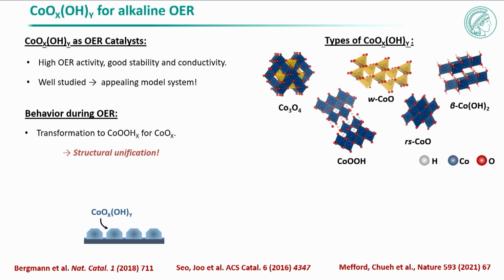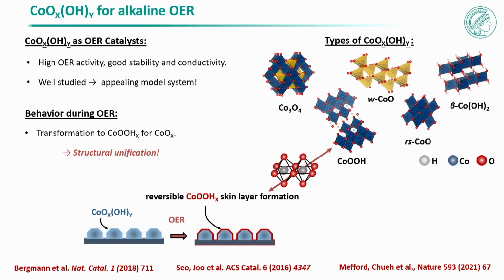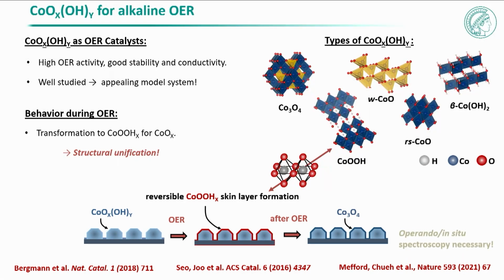So you start with a cobalt oxide or hydroxide, you put it in your electrolyzer, you apply the potential, you do oxygen evolution reaction, and then you make a surface termination. In this case, this cobalt oxide hydroxide, this is a skin layer forming on the surface. And then if you remove the potential and you look at your material again, you get again a cobalt oxide. So for many years, we wasted a lot of time looking at the pre-catalyst, looking at the after-reaction catalyst, but none of them was representative of what was the active material. So there are still things that need to be done.